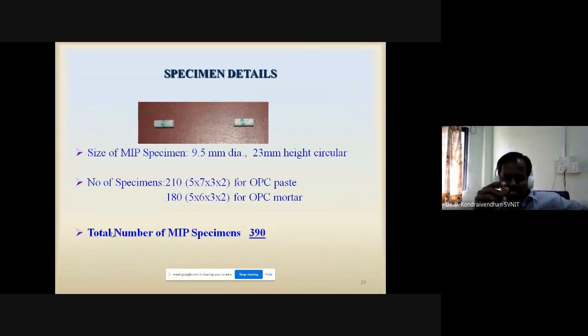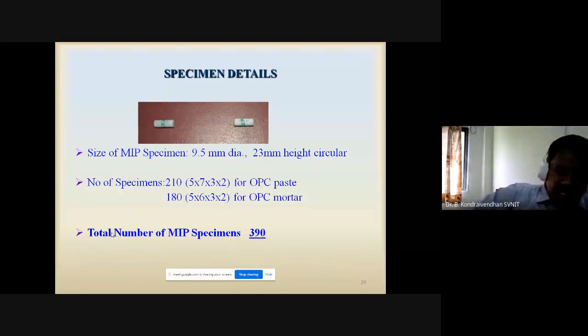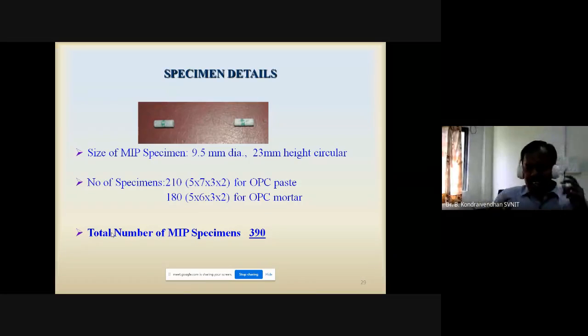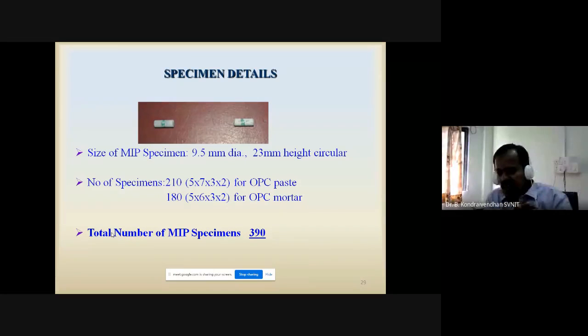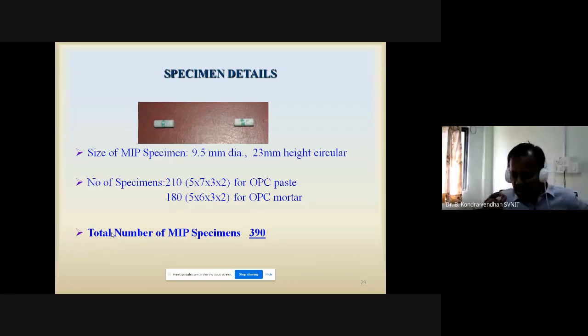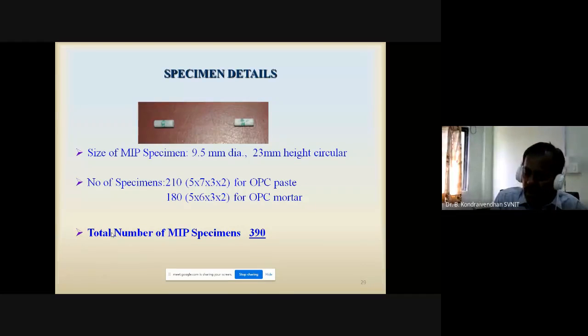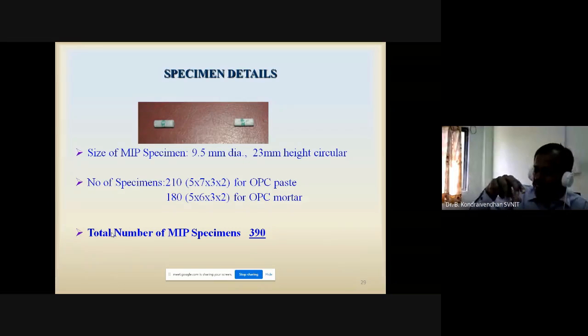So the sample is like that only. Actually, we have to take a small sample only. Whenever we want to test a sample in MIP, there are three possible options. One is to cast a sample of small size, a pellet, a circular specimen of 9.5 mm diameter and 23 mm height. Otherwise, you can take a core from big samples, like from a cube or a beam or whatever specimen we have. From that, you can extract a small core of this size.